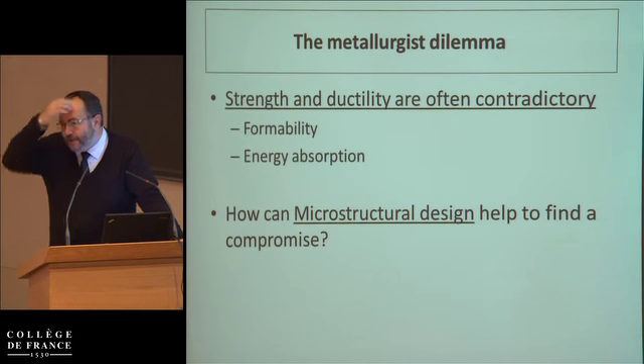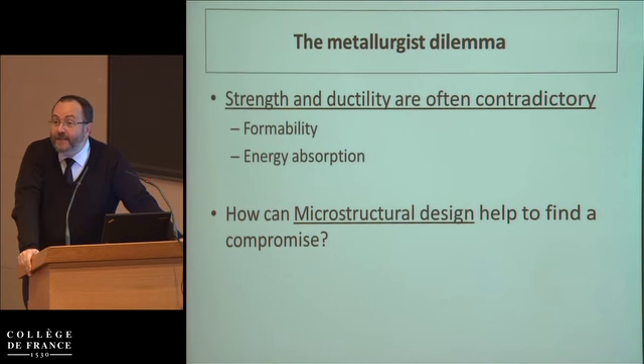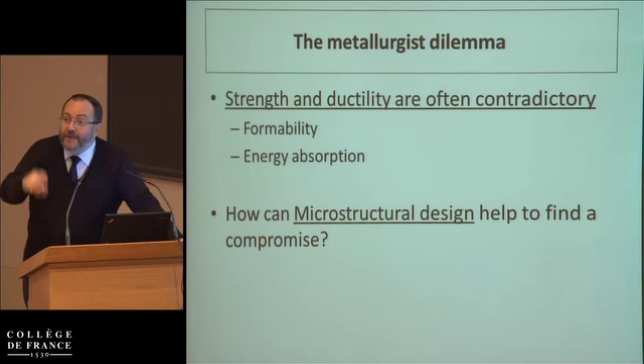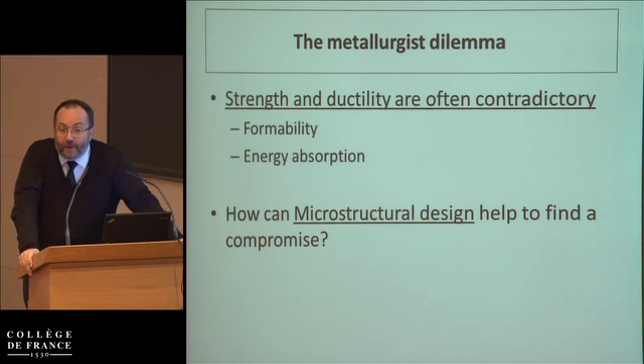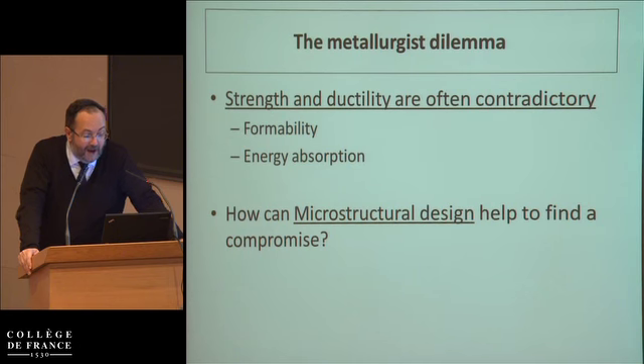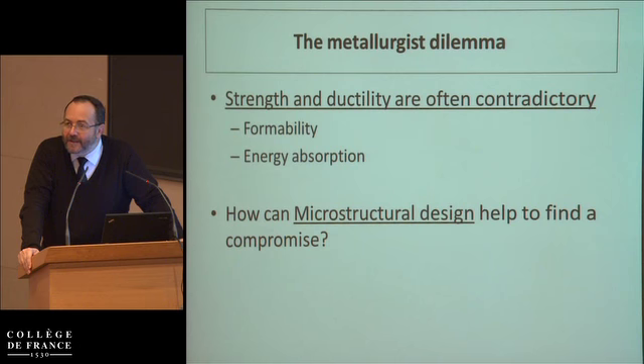You have another reason for that, which is if you have a pre-existing crack, this crack to propagate needs to dissipate energy, and the region in which it dissipates energy is much smaller when the yield stress is higher. So the result is that the crack propagation takes less energy. So these two reasons are the physical basis of the contradiction between strength and ductility.